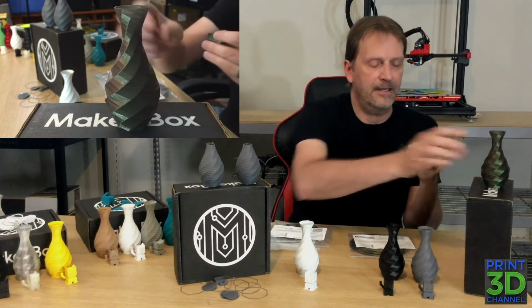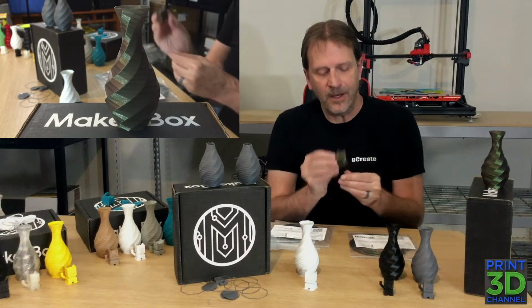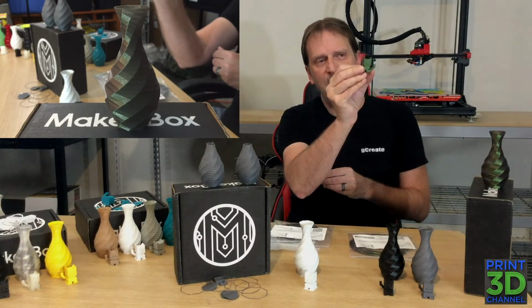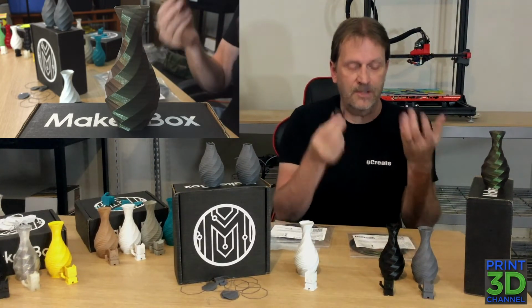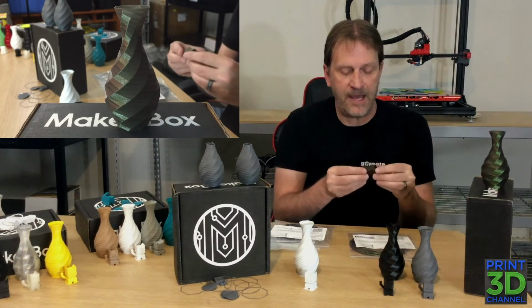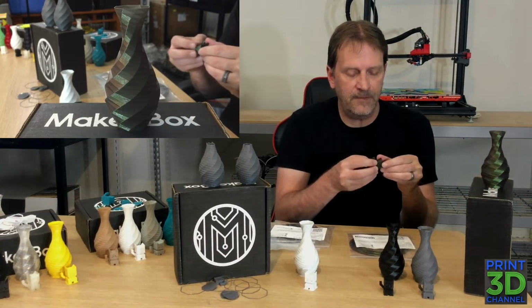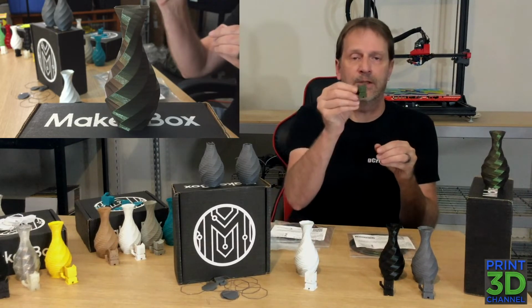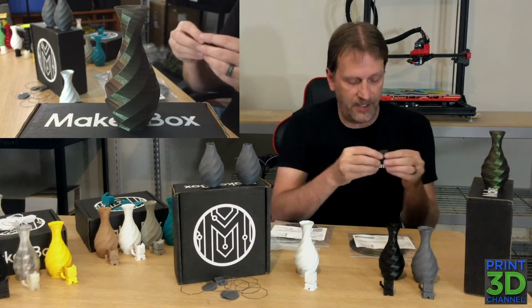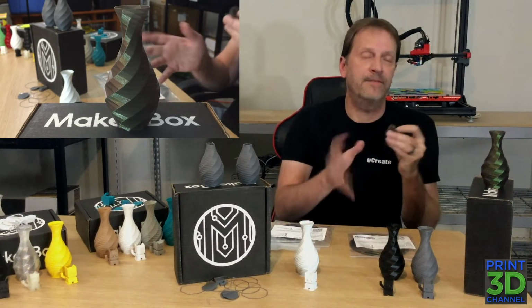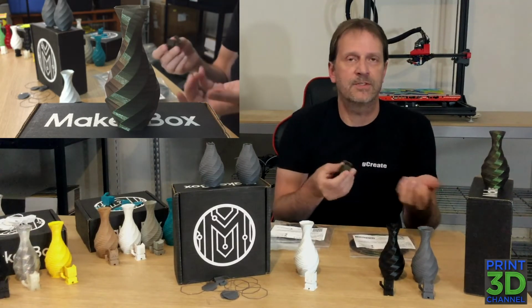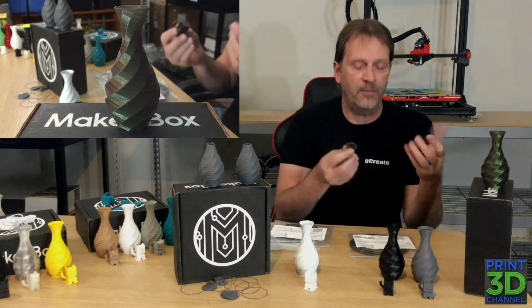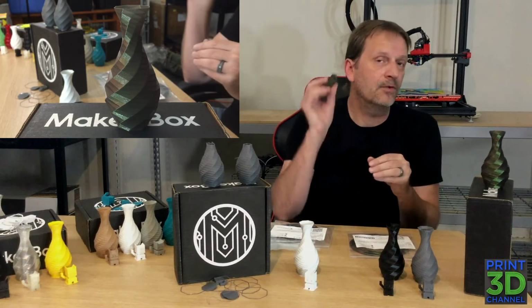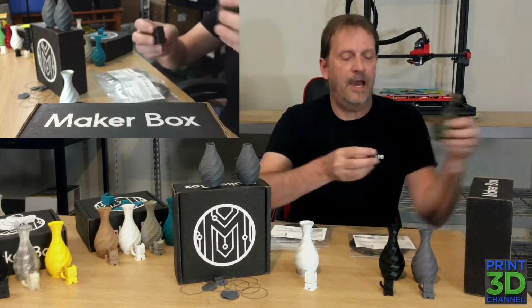Now the Cali Cat turned out pretty awesome. I don't see any stringing between the tail and the body, which is really good. So our 215C temperature was good for that aspect. But I did see a little bit of the meltiness where the extruder stopped in the corners on that. But again, that was nominal. And we did run the bed temperature at 50C, which is my normal print temperature for PLA and PETG on the heated bed. I did use a little bit of Magigoo for an assist on both of these prints. I think they turned out awesome.